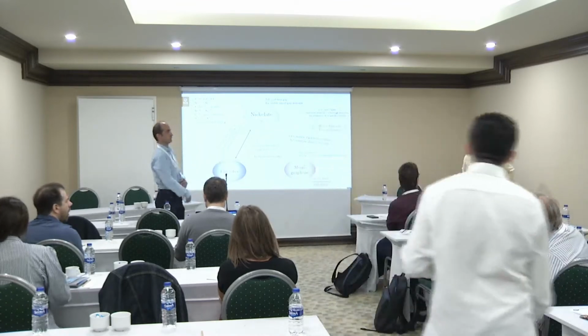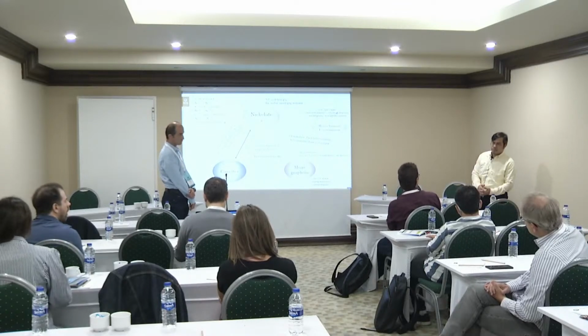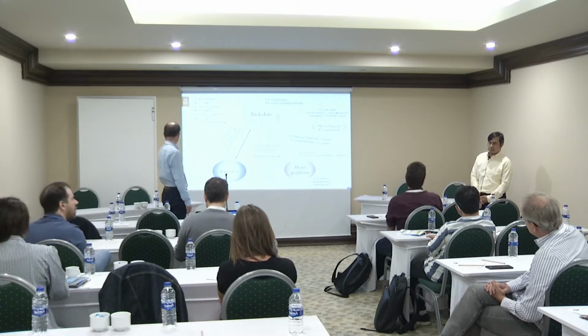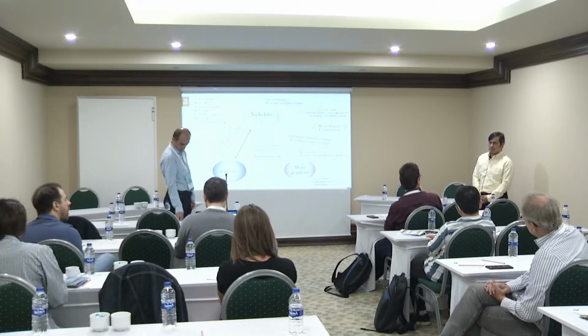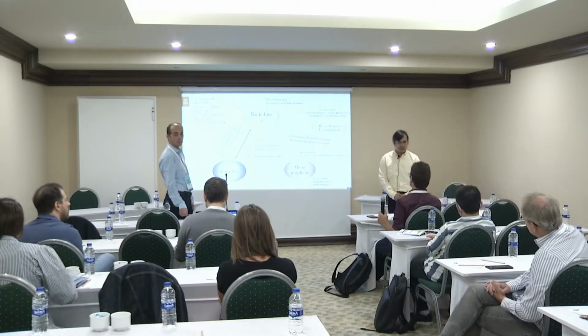So you associated this weak upturn of the resistivity to Anderson localization, which, given that it's a weak effect, is quite reasonable. Have you or other experimentalists been able to prove this more by correlating the strength of the upturn to the disorder, or by applying a magnetic field, so that if it's Anderson localization, the resistivity should then go down? No, yeah, this is something that has to be done, I think, yes. Thank you. That would be a good thing to do.